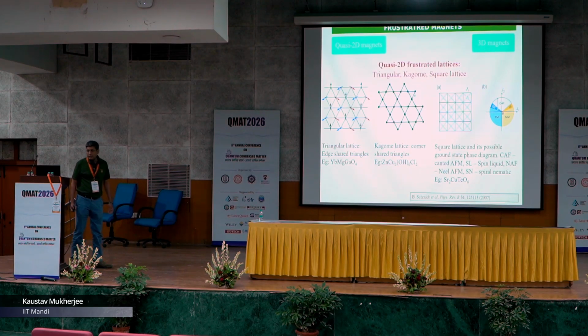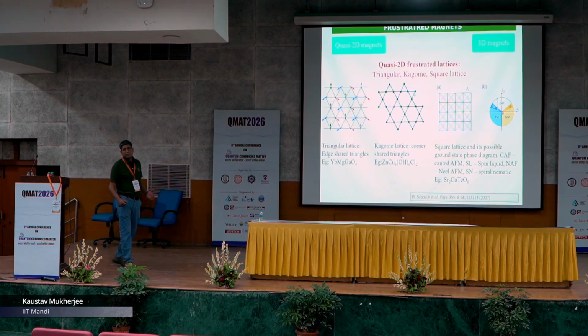So basically what are these triangular lattices? They are nothing but edge sharing triangles, and a very common example of such a triangular lattice is YMgGaO4. Another 2D lattice which has been extensively investigated is the Kagome lattice, which is nothing but corner sharing triangles. The effect of frustrated magnetism has also been reported in various square lattices, where various phases like spin nematic phase, spin liquid phase, canted antiferromagnetic phase, etc. are all reported in square lattices.